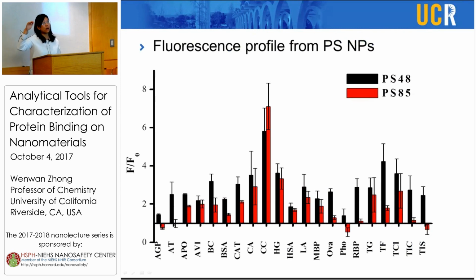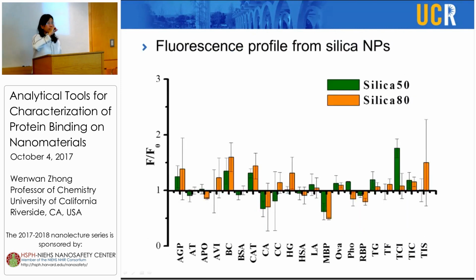But for silica particles, we didn't see very significant enhancement. So one meaning is that compared to the protein by itself, if the labeling of the protein by itself didn't change much, right? If the ratio is larger than 1, that means after incubation with particles, we see more labeling. But if the ratio is smaller than 1, that means after the interaction, we see less labeling, which could be the blocking issue. But the change overall in silica particles is not as large as in the polystyrene particles.